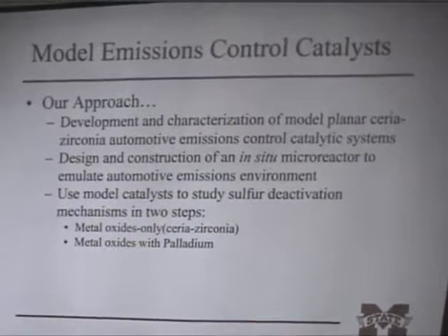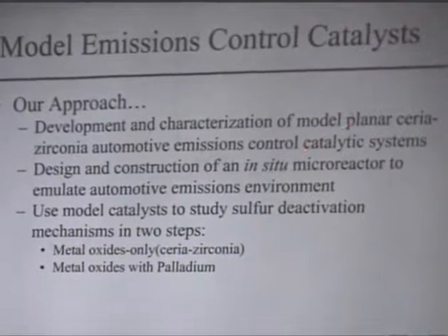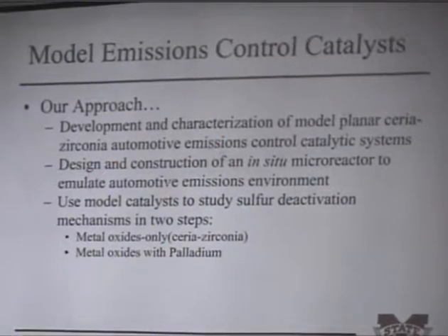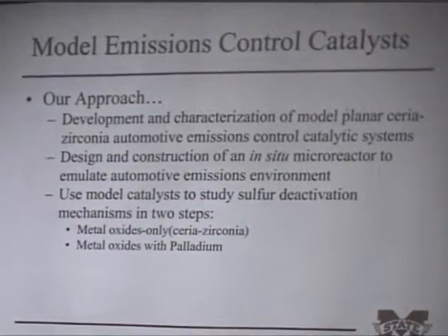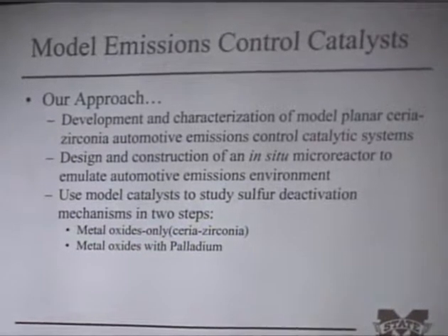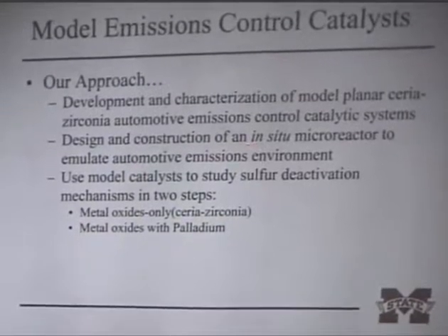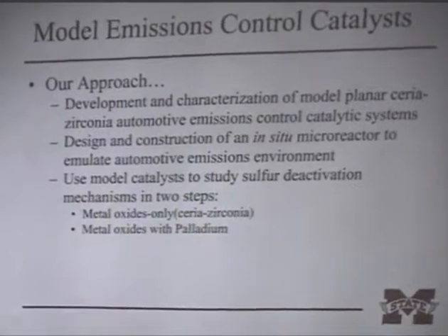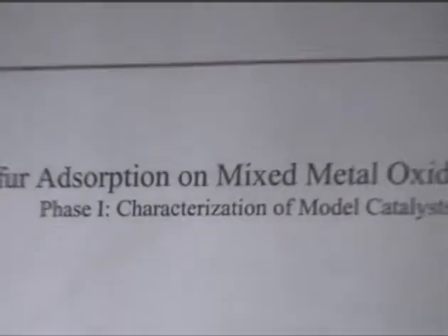So our approach was to develop and characterize these mixed metal oxides first. Secondly, we had to construct a small microreactor hooked up to UHV. This has been done by many groups. This is not terribly unique, but that was the second thing we had to do. And then once we had those done, we wanted to look at the metal oxides, ceria-zirconia, as a function of composition, and how sulfur interacted with these in the form of SO2. Eventually we want to put palladium on top of these, and that's part of what one of my graduate students is doing right now. So the first part is characterization of the model materials.